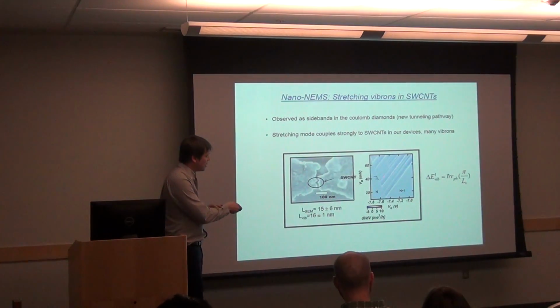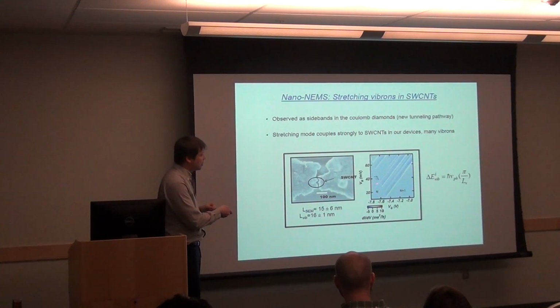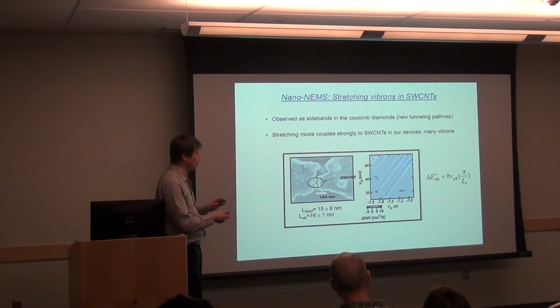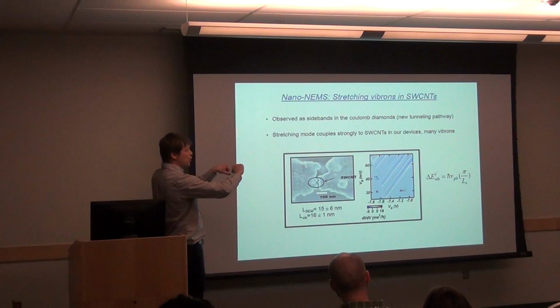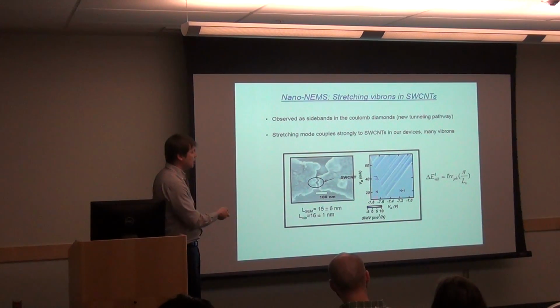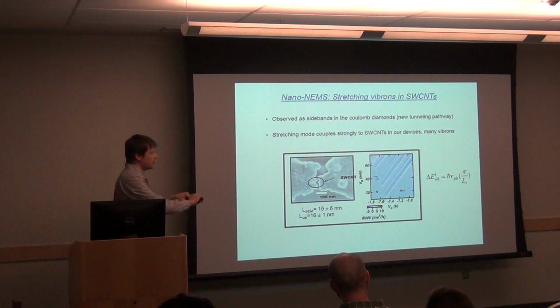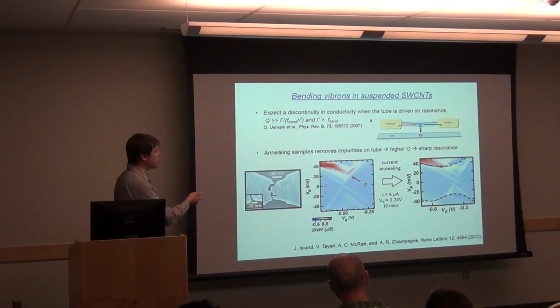And these parallel lines that you can see, the spacing between them gives you the energy of the mechanical stretching motion of the tube. So we can measure there the phonons, the stretching phonons. And the energy matches correctly the length of the device. Now what we can also measure is the out-of-plane motion, the bending mode of the device. We call them vibrons because they're quantized with a different boundary condition. But anyway, the vibrational mode like this.